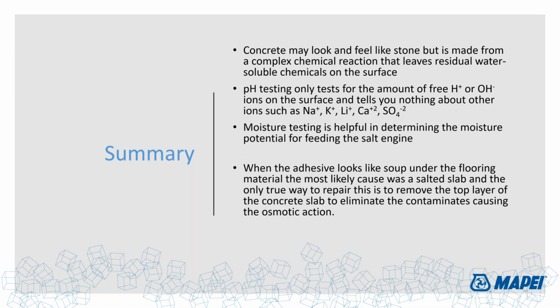So again, high moisture content concrete slabs and high salt concentrations on the surface are huge potentials for salt pump activity and really dangerous for the stability of water-based adhesives. And again, when adhesives look like soup under the flooring material, most likely it's because of this salted slab. And the only way to fix these kinds of problems from happening again, you can't just scrape off the glue and reinstall. You really need to remove the top layer of the concrete, remove that concentrated salt level, get to something that's more normal, and get on with your life, and that will help stop the osmotic reaction.